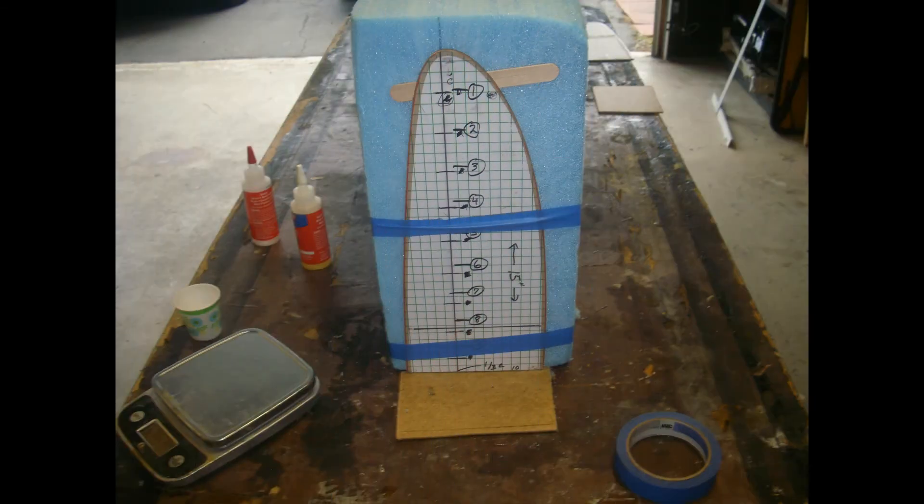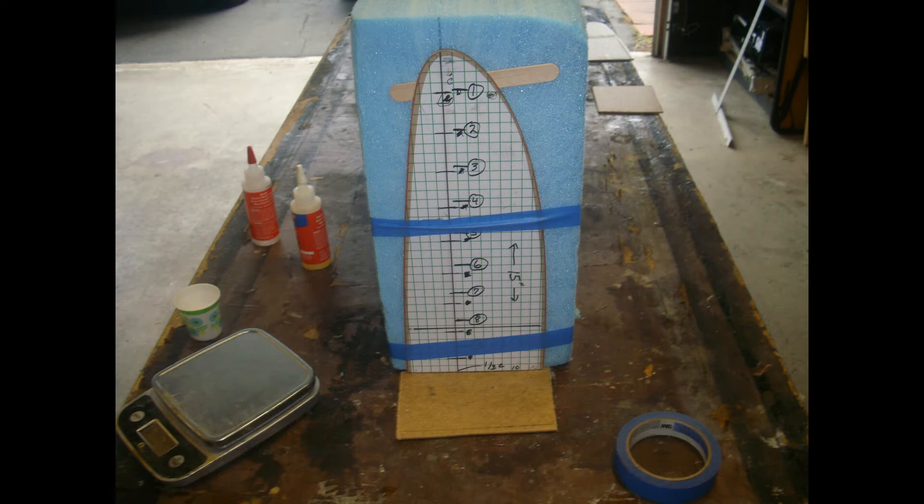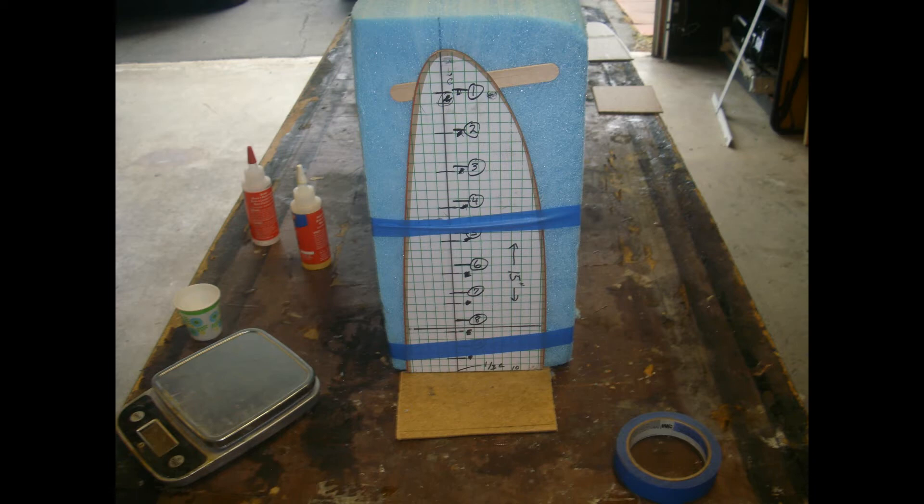Now, we are moving on to the construction of the mold used to produce the D-tube for the leading edge. To keep the mold simple and low cost, I hotwired the shape out of blue foam, two pound per cubic foot material. This material had some problems due to variations in density within the block, causing variances in the shape that had to be filled and sanded later. In the future, I plan on using expanded polystyrene bead foam block, which I know have very consistent density.